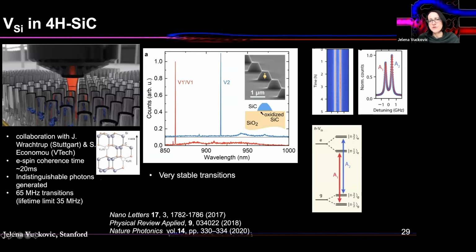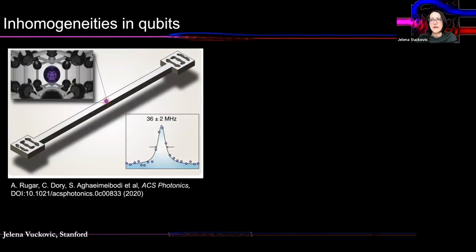And here are some of the spectroscopy measurements from this particular material. You also see very good stability of color centers over hours of time scale. And it also has favorable energy level structures for a lot of interesting proposals, including some cluster state generation. People have demonstrated indistinguishable single photon generation, very narrow line widths, and long electron spin coherence time in this particular material. And silicon carbide is, of course, a very common semiconductor material, which is why we're also very excited about this.